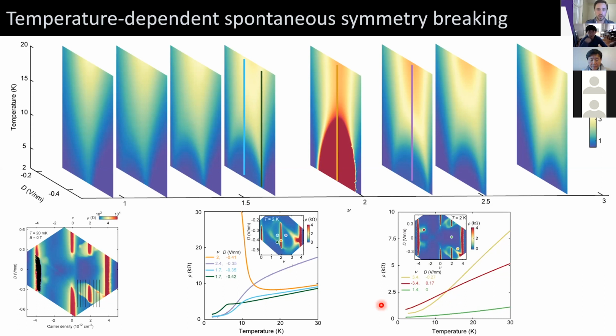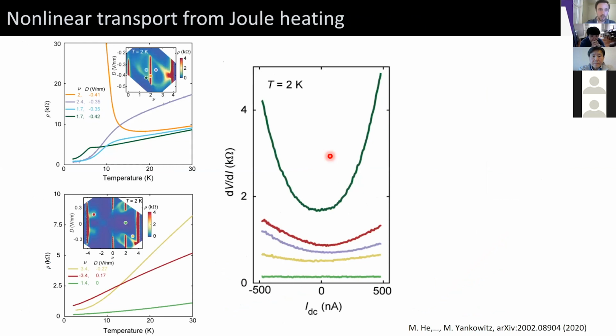All right, so what I want to argue then is basically that these abrupt downturns are actually signatures of this spontaneous symmetry breaking. So in the same way that this insulating state of precisely half filling is a consequence of spontaneously forming a gap in these bands, these metallic states at slight detuning of this half filling still have some remnant symmetry breaking owing to their proximity to half filling. And as a consequence, they still exhibit some unusual transport. Now, these sharp downturns also are qualitatively similar to what you might expect in a superconducting transition.